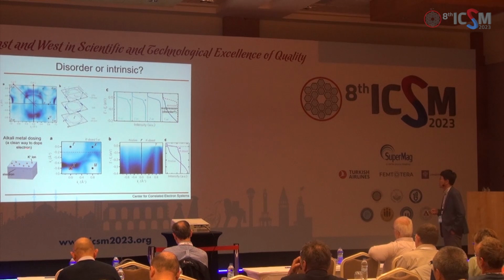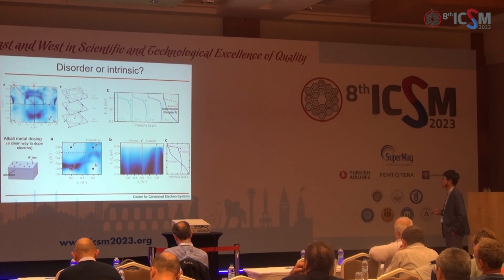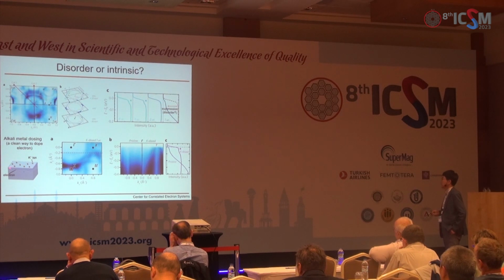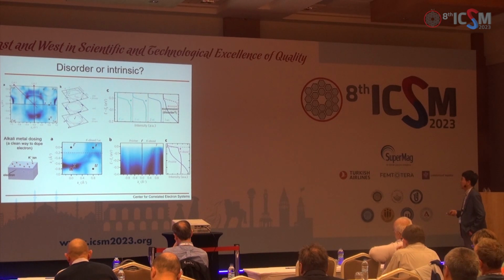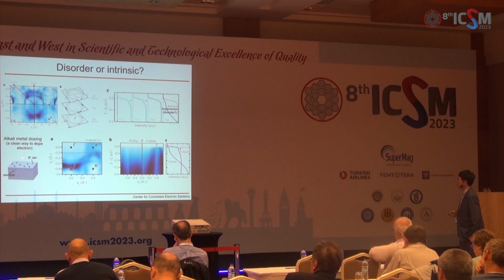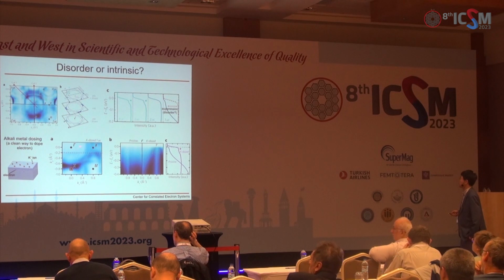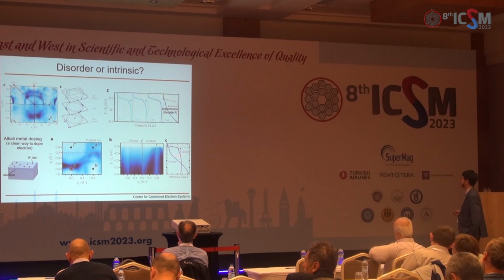So one experiment we did was alkali metal dosing. Basically, we put down alkali metal atoms on top of these films. And what this alkali metal does is that it donates electrons in a cleaner way compared to chemical doping. Now, as soon as we dope a little bit of electron, what surprised us was that as soon as we dope potassium, the spectral weight suddenly grows back to like a fairly thick film of 40%.